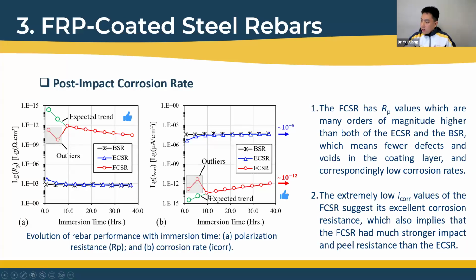But for the red line, the FRP coated steel, the corrosion rate was several orders of magnitude lower than the values of epoxy coated steel rebar and bare steel rebar. This confirms that the coating layer had much fewer defects and damage.